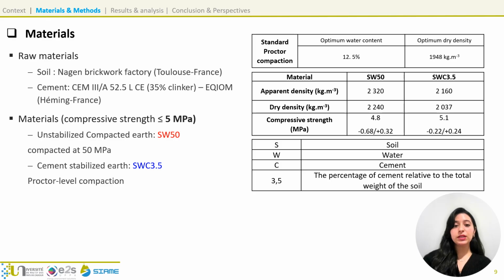The raw materials used in this study are as follows. The soil was obtained from the Nagen brickwork factory in Toulouse, France, and it was characterized using standard Proctor compaction tests, and the optimum water content and optimum dry density are summarized in this table. For stabilization, a CEM III/A 52.5 L cement containing 35% clinker was supplied by Eqiom in Heming, France. The materials produced were designed to have a compressive strength of approximately 5 megapascals, comparable to hollow fired bricks used in buildings.